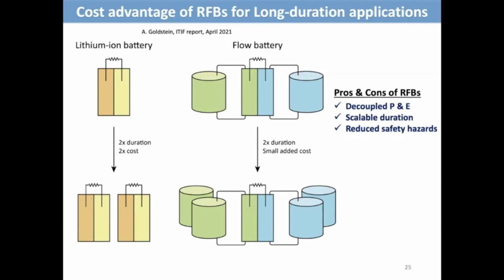This is a schematic taken from a recent ITIF report, which nicely shows that for a lithium ion battery, 2x duration means 2x cost for a particular application. But for a redox flow battery, 2x duration will just need a small added cost on top of the original system, thanks to its decoupled power and energy and scalable durations. Also, an important feature of flow batteries is that they have much lower safety hazard because we separate the positive and negative electrolyte. So they will not short-circuit or self-discharge easily if we stop the pumping. Therefore, there is a lot more control than with a lithium-ion battery.